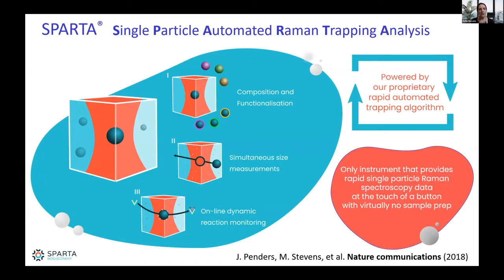And what SPARTA can do is it can use an optical trap to trap an individual nanoparticle and measure its chemistry. And so we can then learn about its composition and how the particle is functionalized, and we can correlate that to the size of individual particles as well. So do simultaneous size measurements and even measure real-time dynamic reactions on the surface. And this is all powered by our own software and coding that we've written in an instrument that you can now use at the touch of a button.